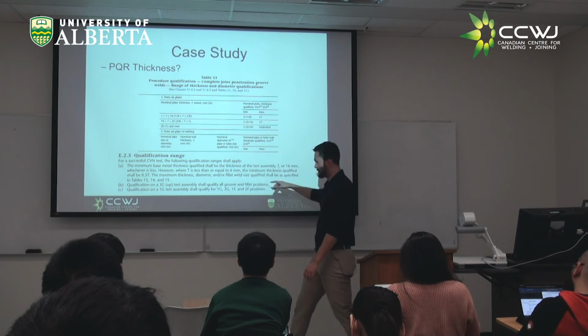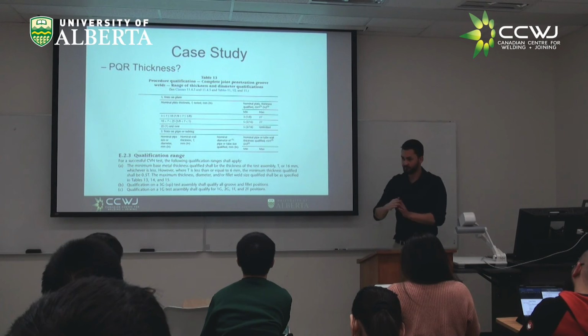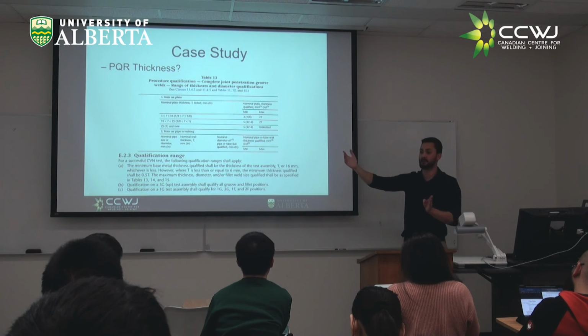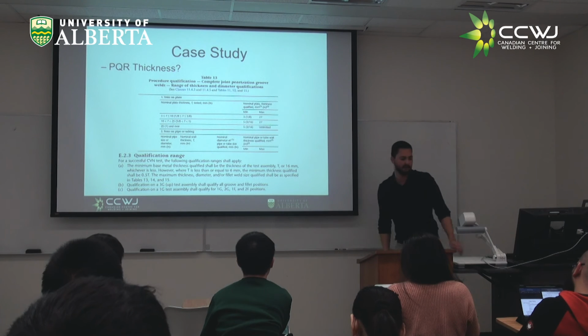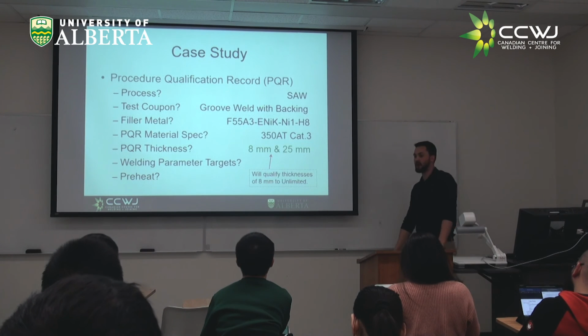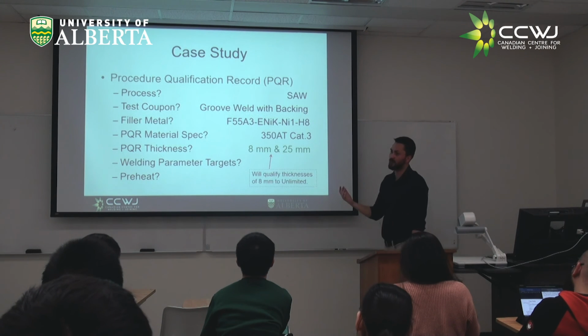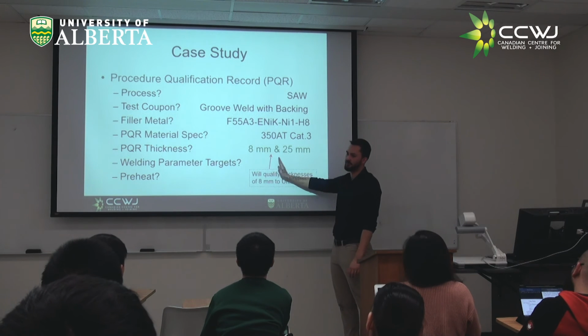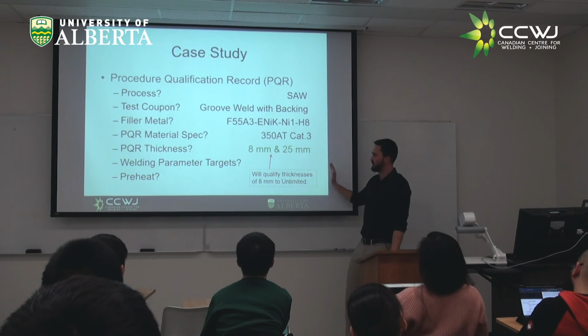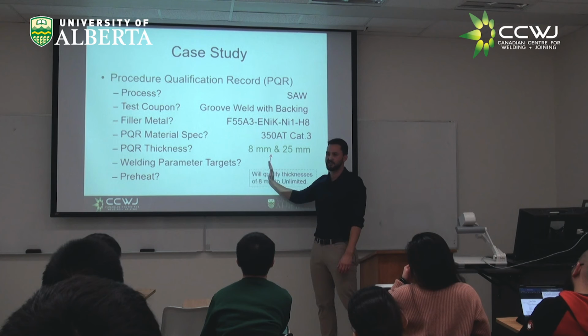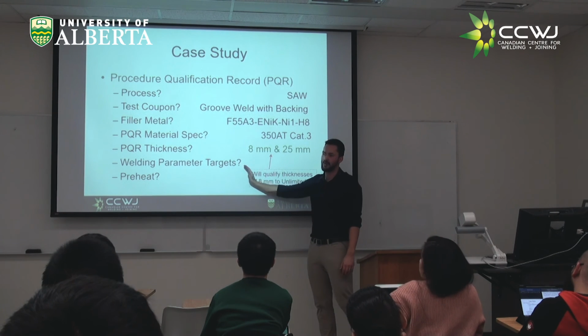So what you have to do is go back, and then it says that for any of your thicknesses that you use, you essentially get that thickness and then up to double that thickness. So what we would do in this particular case is we would test on an 8 mm plate and then a 25 mm plate. So this 25 mm plate is going to cover the thickness ranges of 16 to unlimited. This 8 mm plate is going to cover 8 to 16 mm. And you have to play games like that.